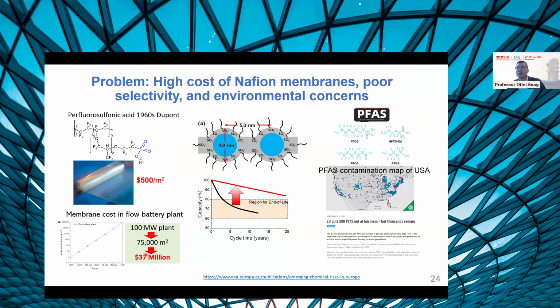It's a huge investment. And there is also a scientific challenge, because the Nafion membrane has a hydrophobic backbone and hydrophilic side chains. When they absorb the water electrolyte, they form self-assembled water channels with relatively larger size. That means they're not so selective. In the batteries, especially the new generation flow batteries, the crossover of the redox species is a serious issue. That means the capacity will rapidly decay. So we need to develop better membranes with high selectivity.